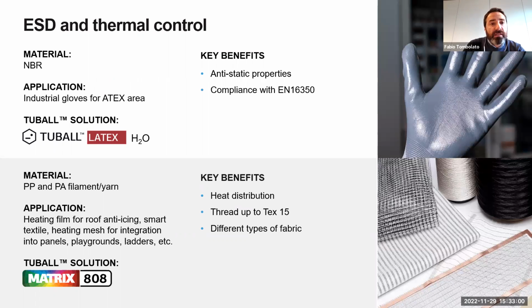Industrial gloves for ATEX area can be achieved using the chemistry of NBR together with our Tuball Latex. Antistatic properties can be achieved compliant with EN 16350. Different application, heating film for roofing anti-icing can be achieved modifying the yarn, in this specific case polypropylene and polyamide, with our Matrix 808 to achieve heat transport.